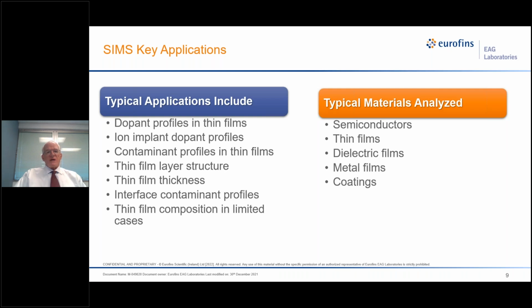So what applications do we have in SIMS? The key applications are dopant profiles in thin films. We do lots of ion implantation profiles, contaminants in thin films, thin film layer structure, thin film thickness, interface contamination profiles, thin film composition in limited cases. The materials analyzed are semiconductors, thin film, dielectric films, metal films and coatings, and I will throw in there everything else.